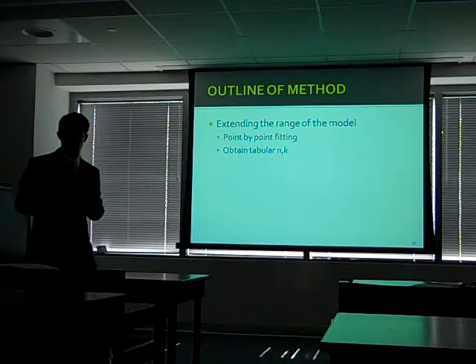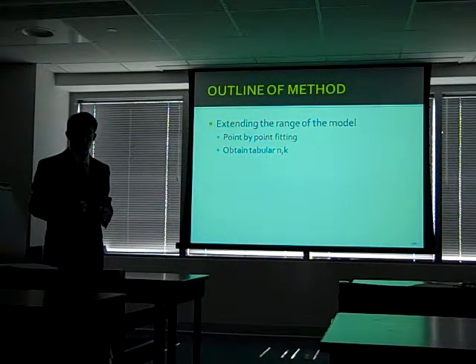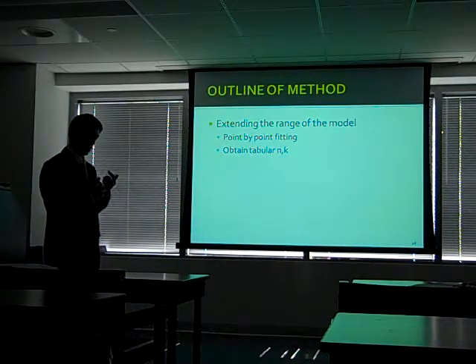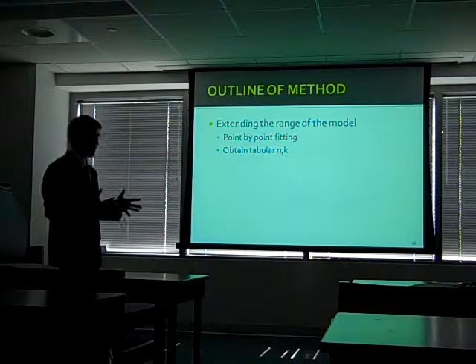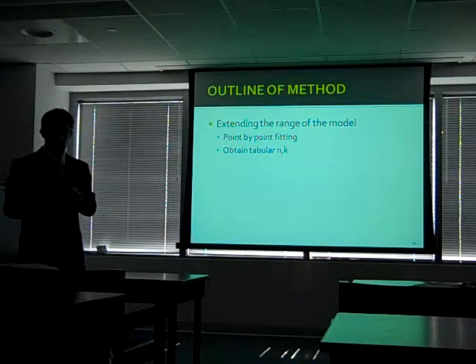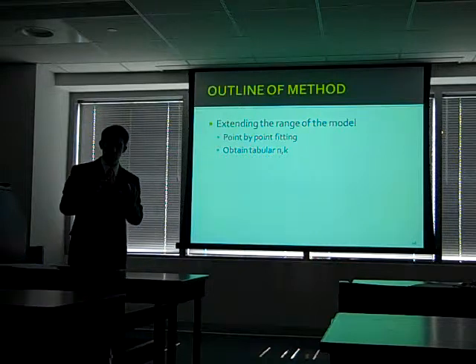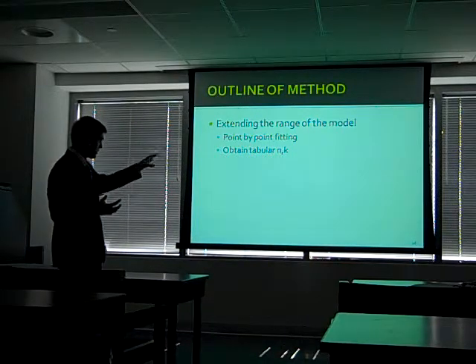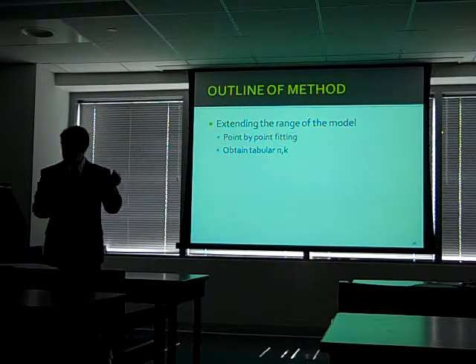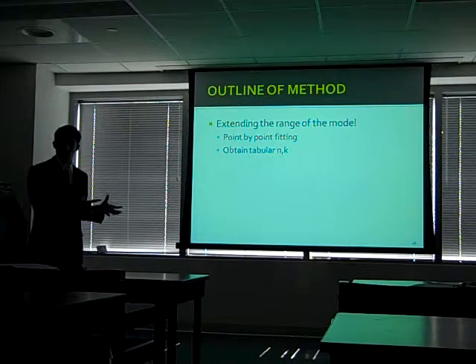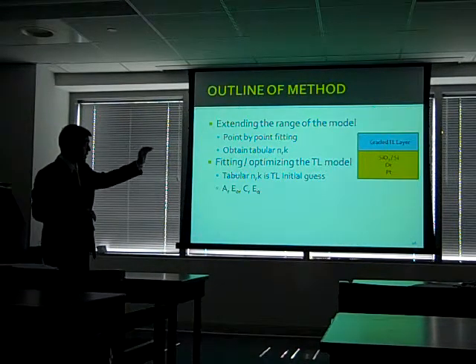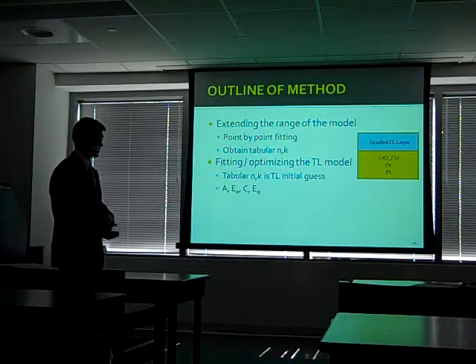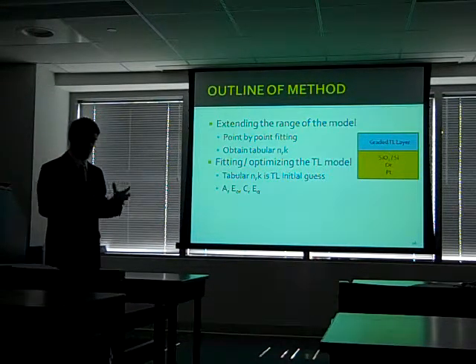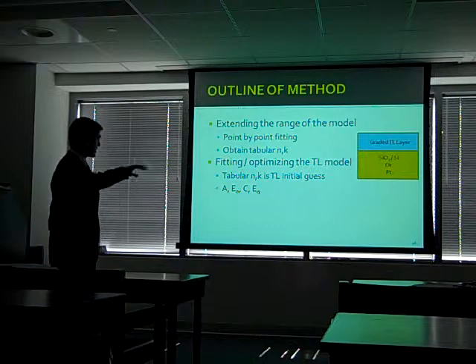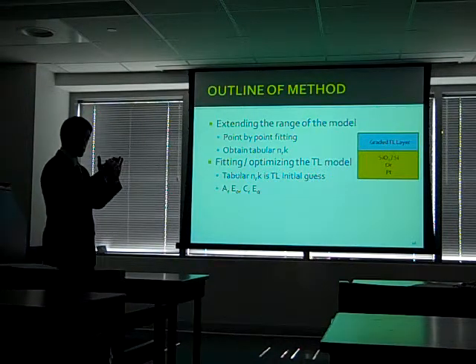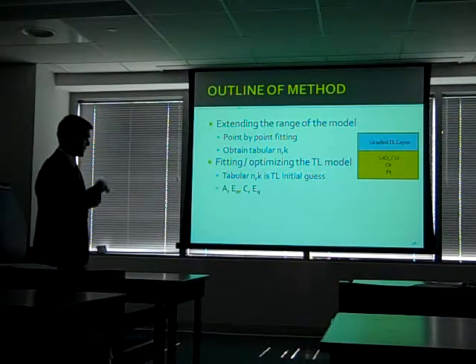So to extend the range of the model, we'll start by doing a point-by-point fit from long wavelength to short wavelength. And this gives us a tabular index of refraction N and K. Although, as a caution, these optical constants are not physically reasonable. The purpose of them is to provide an initial guess to the Tauc-Lorentz parameterization. I mentioned before the Tauc-Lorentz is the way that we're going to model the band gap. So this tabular N and K serves as an initial guess to start off the Tauc-Lorentz model.